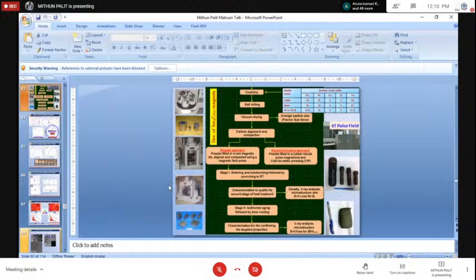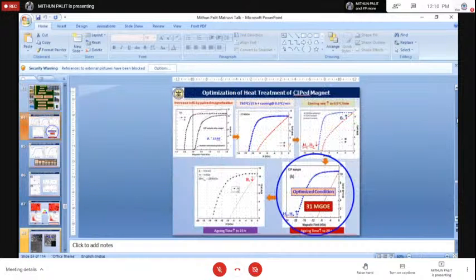There we pour the powder into a rubber mold, and the rubber mold is completely sealed with different mechanisms, and after sealing it is put into a water tank, and in the water tank we apply very high pressure to compact it from all directions uniformly, and this is then processed by heat treatment and other routes. In this method you can make a very large magnet. In fact, we have developed different magnets in this process.